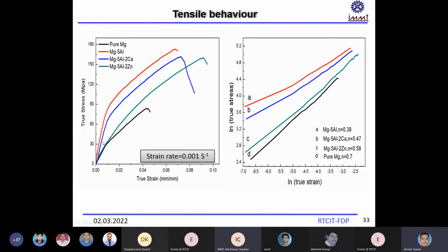You are getting more strength when it is only aluminum, but the ductility is reduced. So to remove that gamma phase, we have added calcium, but with the calcium addition, you can see that this has an effect. It reduced the strength, but ductility is also not improved. Yes, no improvement in ductility, because the calcium forms another intermetallic, and that also is brittle, and that's why the ductility has no improvement.